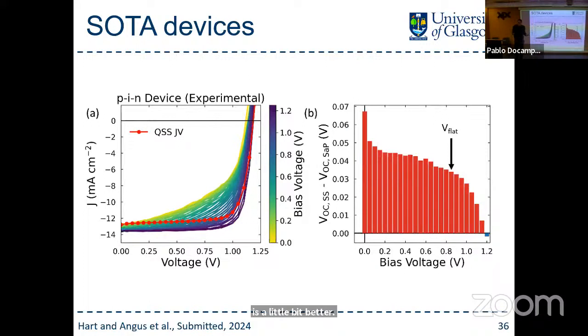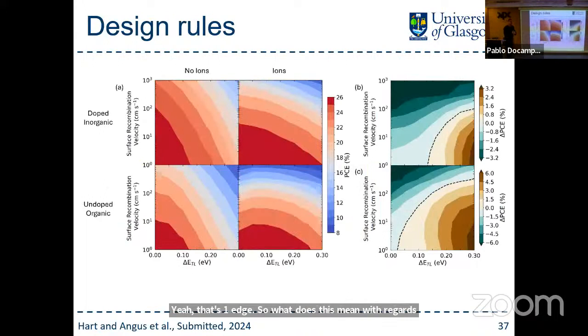So what does this mean with regards to how you should optimize your device? Well, we took a data set using the parameters for this really high efficiency device, and simply looked at varying the surface recombination and the band offset. The interesting thing is that when you've got ions, you're less sensitive to offsets at your contacts. Okay, but you're more sensitive to surface recombination.